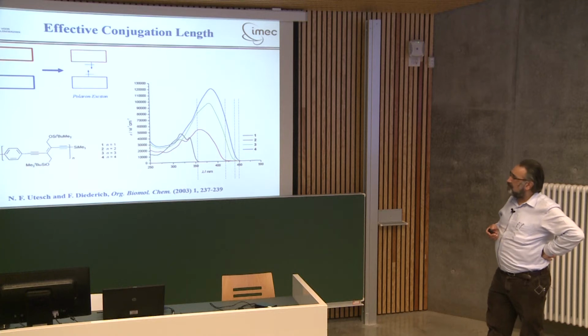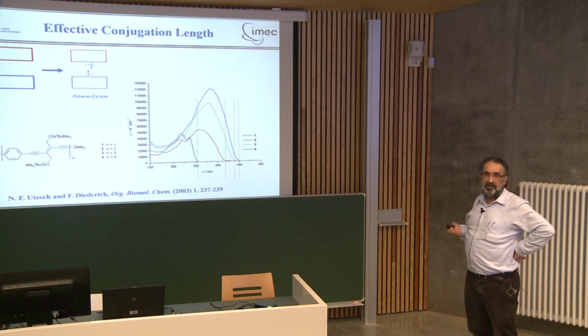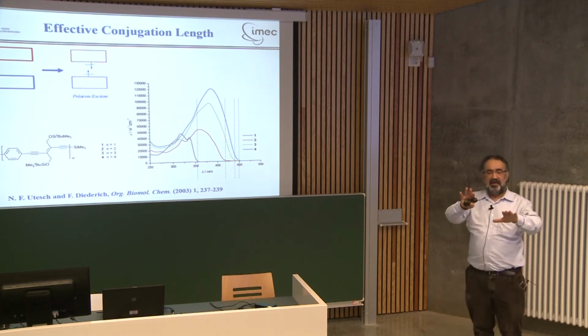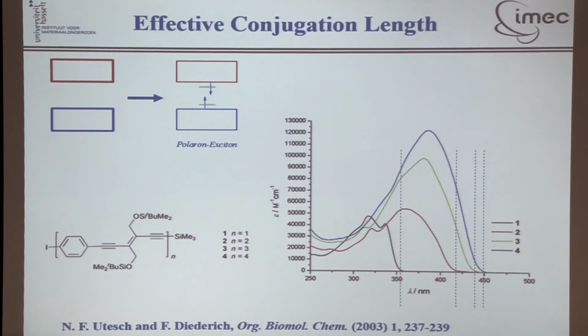Well, quite often, and in a lot of papers that you find in literature, they typically refer to the fact that this is a flexible system and this is not flat, so you have torsion angles, there's a kind of angle between the different planes, and so the interaction is not that effective, and by consequence, your band gap doesn't decrease to the extent that you would expect. Okay, it's quite often said, this effect exists, but this is not fundamental.